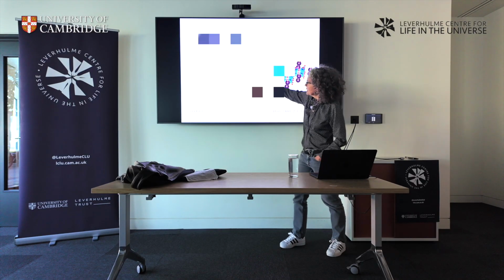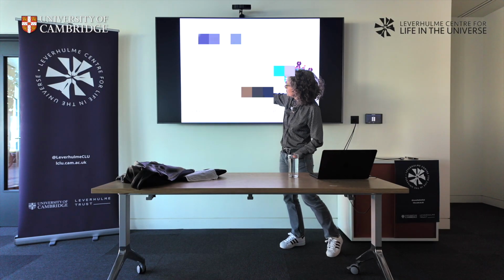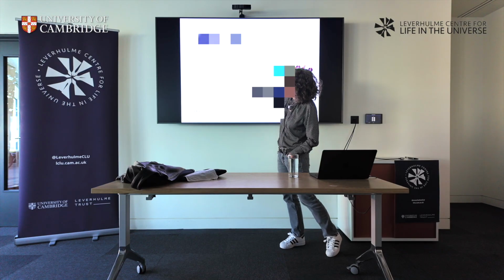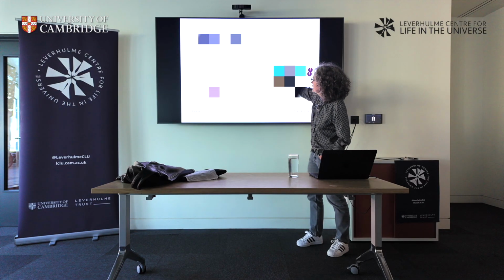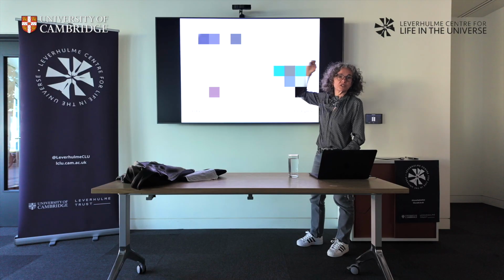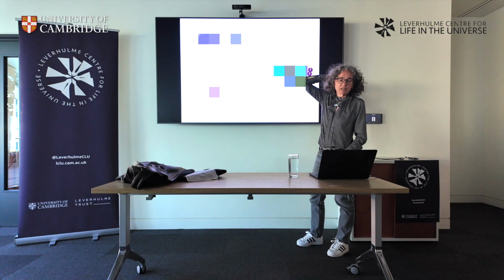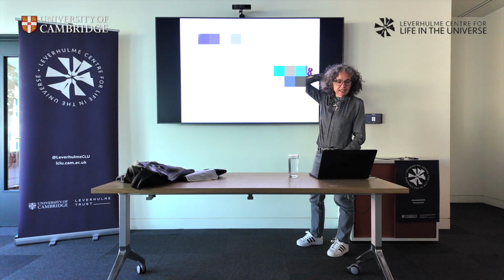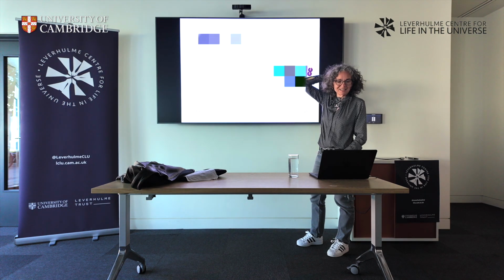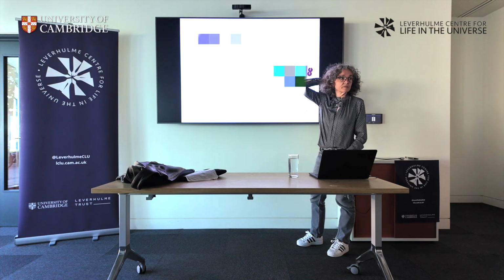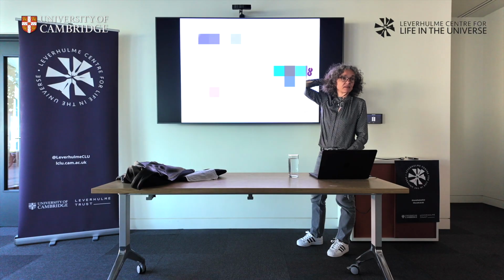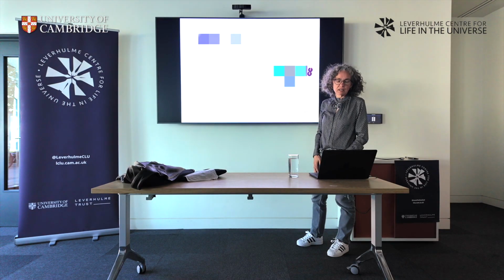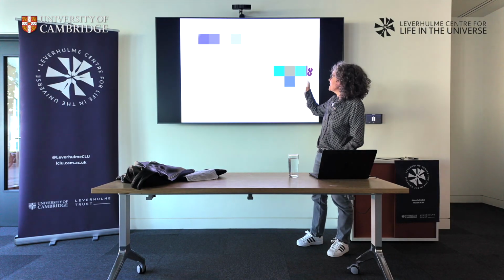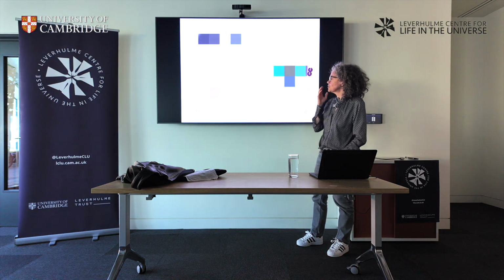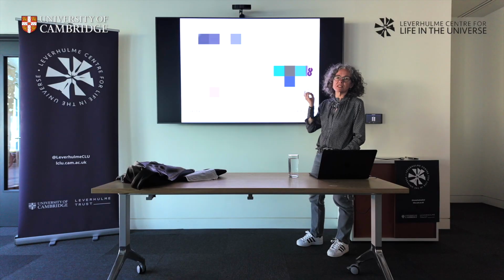Actually, the second peak here, which I haven't tried to fit in this figure, is the next potassium that you see. So it looks like it's not xenon to silicon, it's xenon to potassium substitution that we have. And this is stable back to room conditions. We also tried reheating it to 500 C. It's still there. The bond is still there.